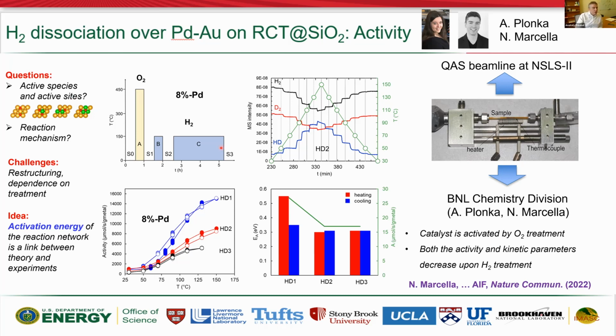So the activity measurement was studied by mass spec, and you see here the example of HD formation at different temperatures. It was clearly some kind of deactivation going on, because in the initial stage, after activation in oxygen and preliminary annealing, we have 1, 2, 3, 4 different states in which the catalyst was measured after different treatments. So the first treatment was in oxygen, and the sample was called S1. The second treatment under hydrogen, S2, and then repeated treatment under hydrogen, S3.